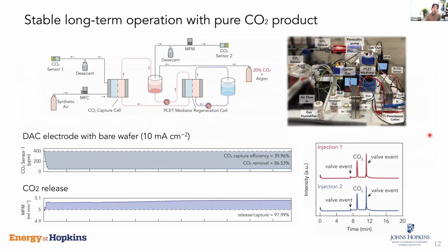And then we tested the long-term performance of our EDAC setup, with a schematic shown here. And this is our device in the lab with two electrochemical reactors. In one of the electrochemical reactors, we're sending air in and measuring the outlet CO2 concentration. So this is the DAC electrode sensor data. And on the other side of the cell, we're coupling that with PCET mediator, and we're monitoring the amount of CO2 being released through this regeneration step. So that's the mass flow meter data showing how much pure CO2 is being regenerated.